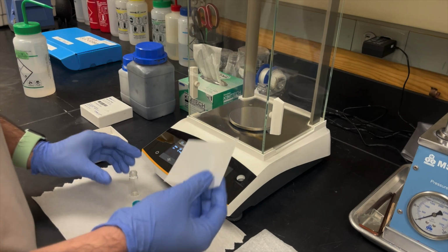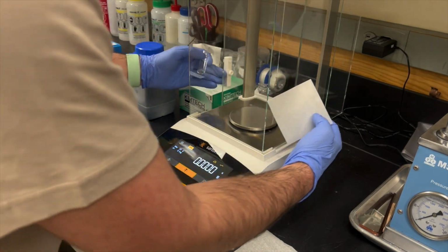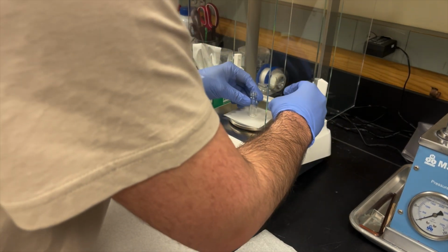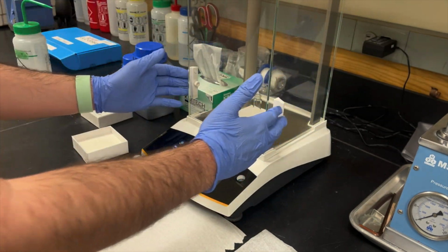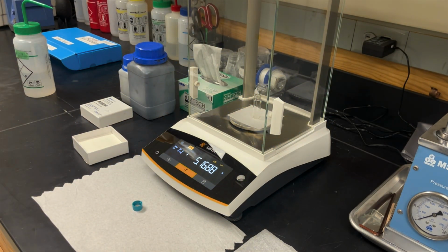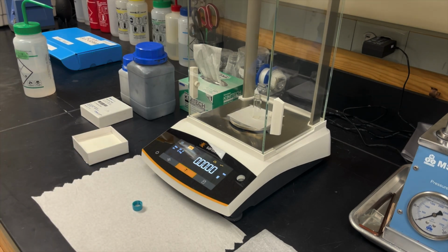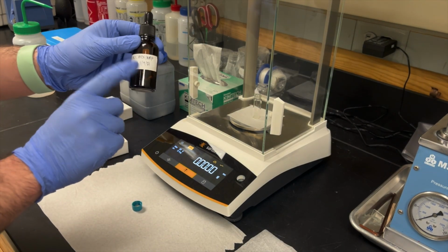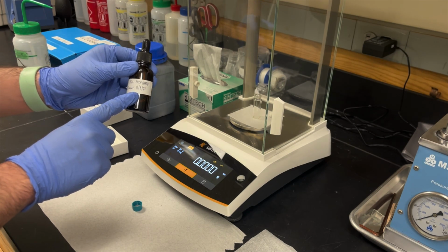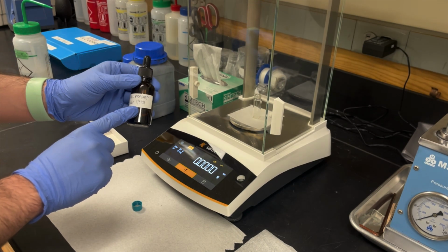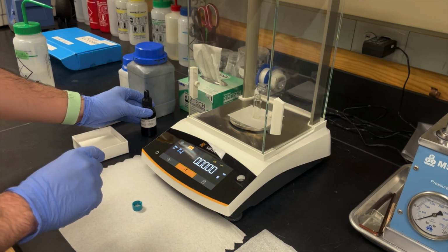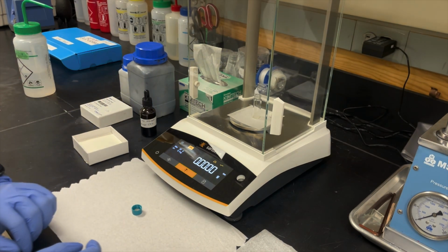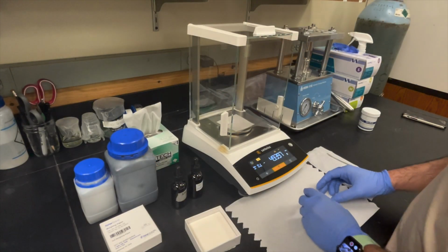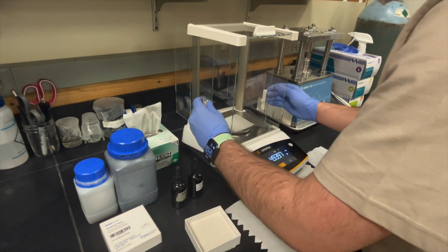As previously mentioned, we were going to try and weigh our material afterwards to see how much that we would have lost. With 10 milligrams of carbon black and 80 milligrams of active material, ideally there should be around 90 milligrams of material left over. So before we add that binder solution, we're going to weigh that out. But first, since we've tared it, we'll now be able to add our material and see just how much is in there.